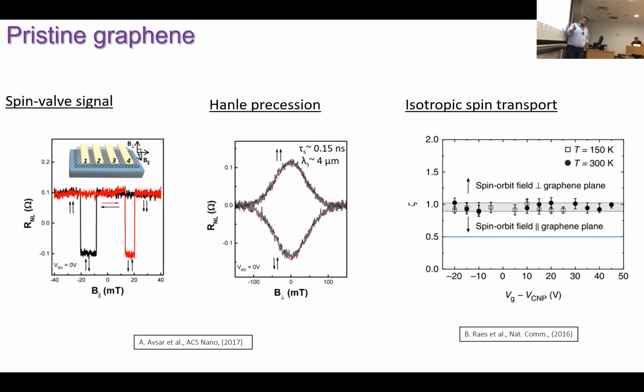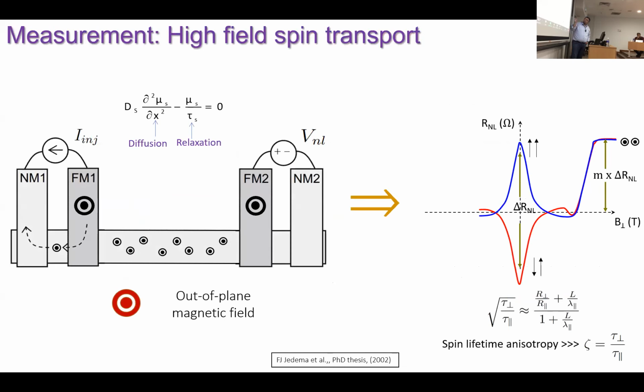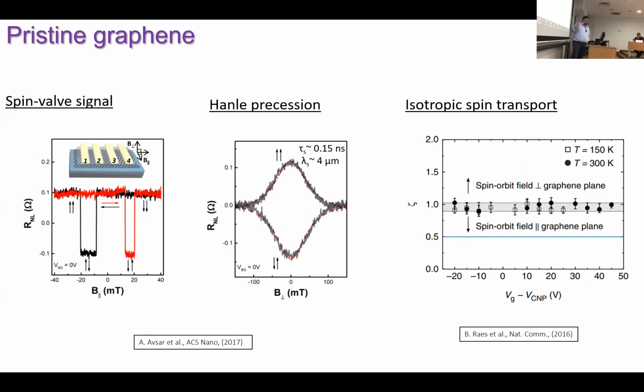So these are the main measurements we have. You see spin switch, Hanle, everything looks good. And this anisotropy that I was just introducing you here, the ratio of this signal to this signal, for pristine graphene we get exactly 1. So this material is isotropic. There is no difference if the spins are propagating in plane or out of plane. The spin transport properties are identical.